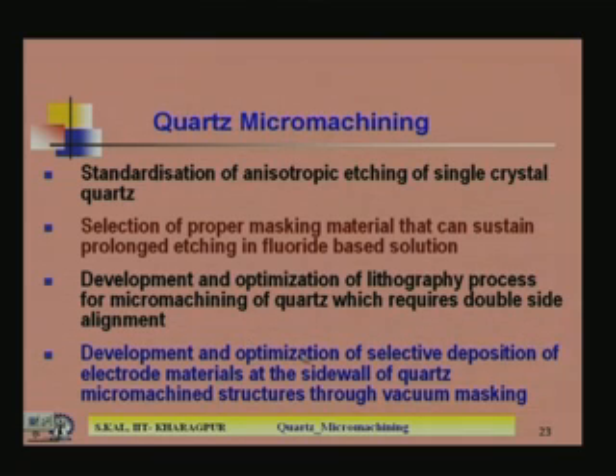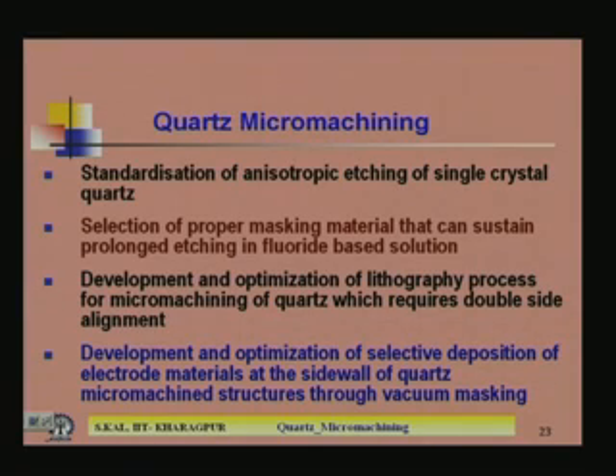Fourth point is the development and optimization of selective deposition of electrode materials at the sidewall of quartz micromachined structures through vacuum masking techniques. Because if you make a quartz sensor, not only on the top and bottom surface you metallize and get the electrode, in many cases it may require a sidewall electrode. On the sidewall you have to give the metal electrode to improve the Q value of the resonance structure. So, that sidewall electrode formation is not easy. For that you need a special kind of technique which is known as the vacuum masking technique, and that will help you to get the sidewall electrode, as well as conventional techniques can be used for bottom and top side electrodes.